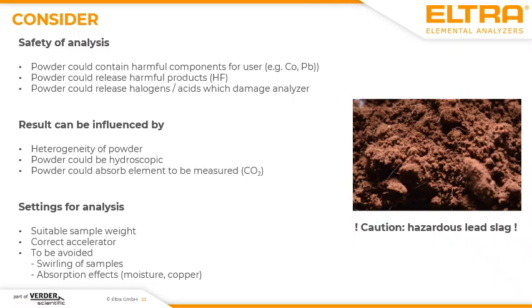Besides the safety information, please be also aware that you have to consider the heterogeneity of the sample. Here I show you a picture of a very hazardous and heterogeneous lead slag, because this kind of sample is very critical for this analyzer. You have to be aware of the safety when you prepare the sample, but this sample is also heterogeneous. It can absorb water, and when you store it for a long time in air, it can also absorb CO2. This is an effect you also have to consider with a finely divided powder, because storing could falsify the results.